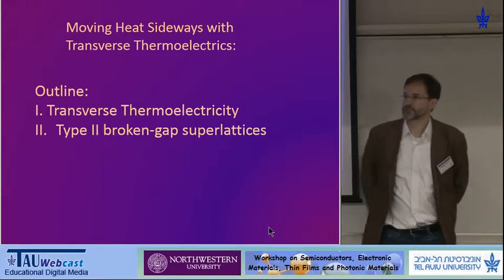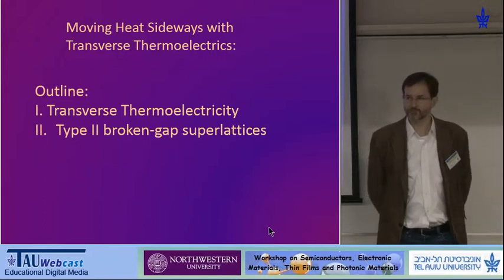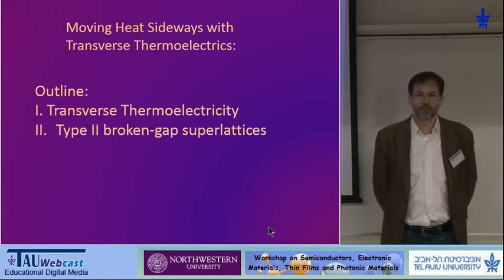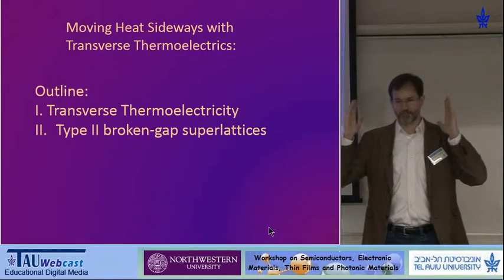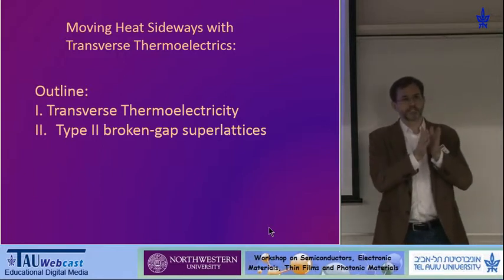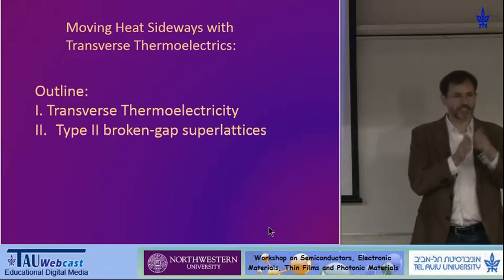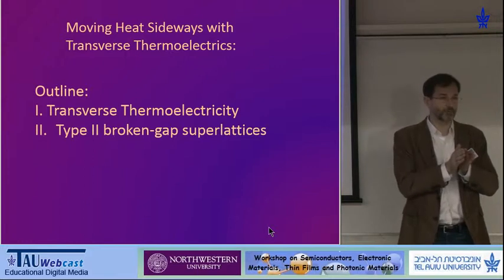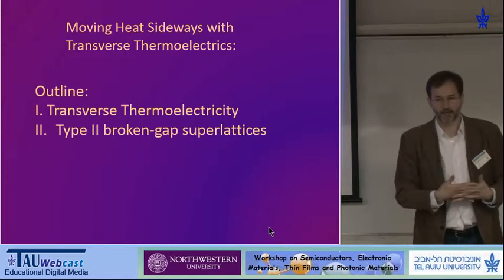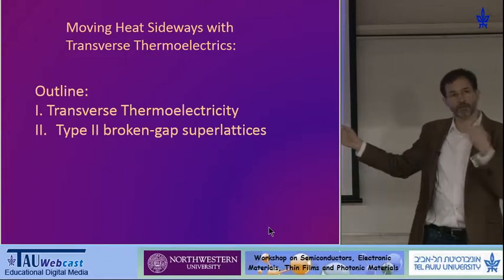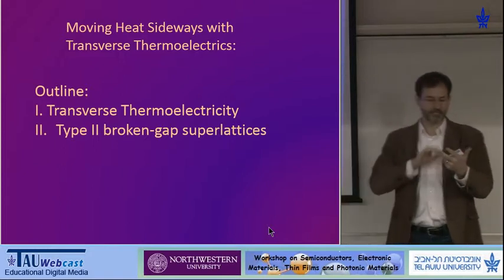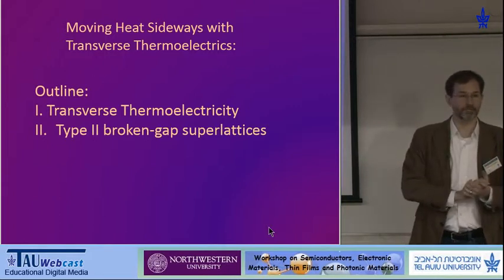The ZT values in these materials are very small — this one was about 0.02. A competitive thermoelectric nowadays is ZT = 2, and ZT = 1 is the standard. But given more than 100 years of research on standard thermoelectrics versus only two years on this paradigm, we'd like to think it should be possible to find ZT = 0.1, 0.5, 1, maybe even ZT = 2 in transverse thermoelectrics in the upcoming decades. The challenge I pose to the material science and chemistry communities is: these materials exist, now we have to do the material science, simulations, band structure calculations, and synthesis to find the best candidates.